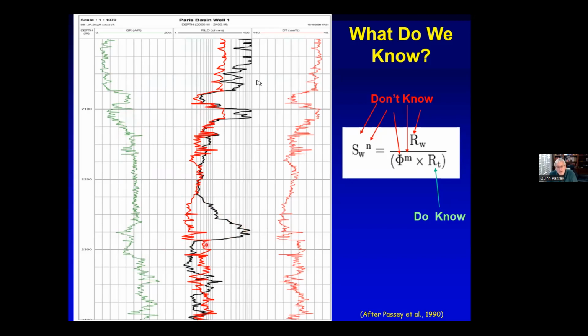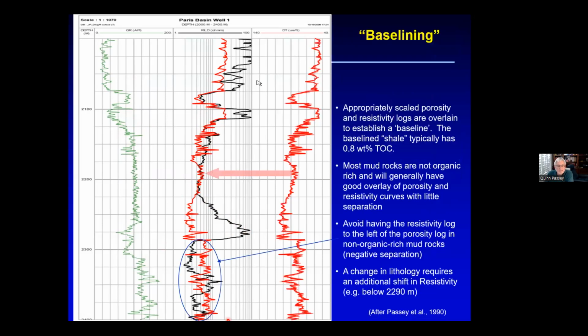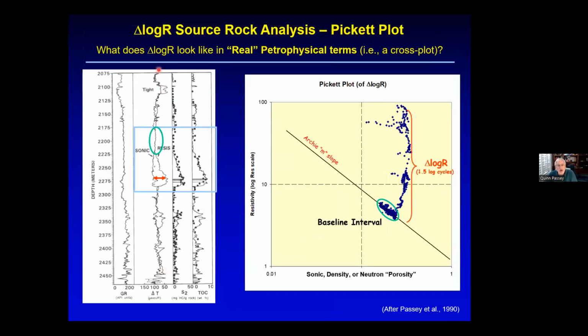Now down below here, it's a different lithology. And so we actually have to re-baseline for this interval down in here. Once we've re-baselined and put it all back together, now we've got the curves overlaying. We did a baseline shift here. And when we did that baseline shift, then we can see the areas that track. That means no hydrocarbons. And now, a lot of petrophysicists don't really like the delta log R.